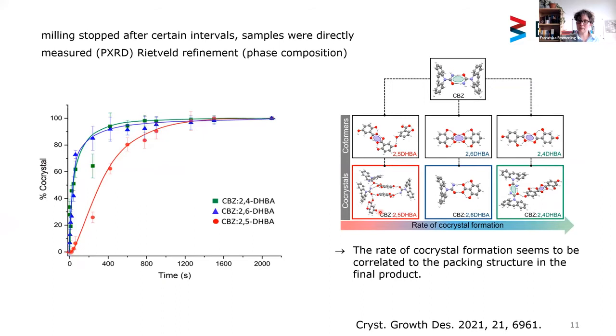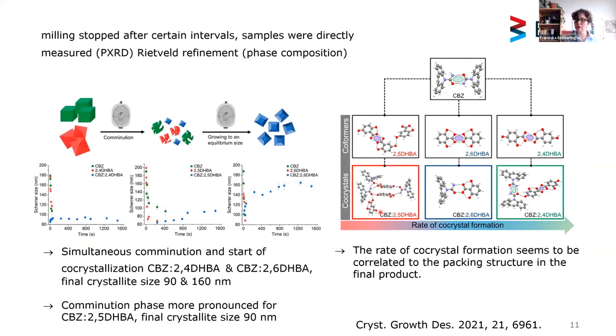We also looked at the size of the crystallites in this case, which is usually reduced in the first stage of milling due to comminution. So we have usually smaller particles, but here you can see for the 2-4 and also for the 2-6 compound, the formation of the co-crystal starts right after onset of milling. So within the first 10 seconds, we already see reflections of the final product. So in these cases, the comminution is not a prerequisite for the reaction. It starts immediately, whereas in the other case, we can see that there is a short delay and it takes some time before the co-crystal is formed.